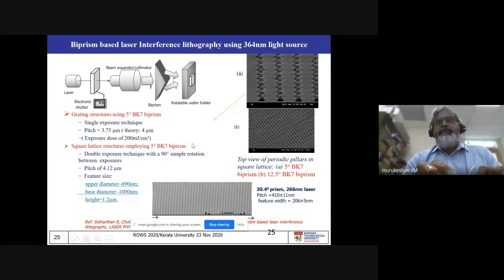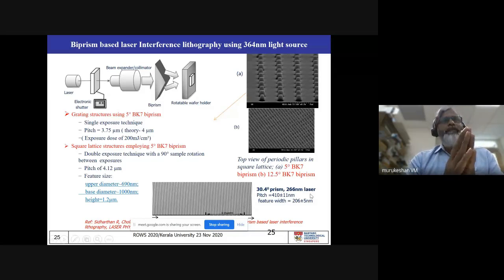Now, coming back to the feature size, you can see here that this is a single exposure technique. You can get a pitch of 3.75 micron, very close to the theoretical value, with an exposure dose of 200 millijoule per square centimeter. We can also get square lattice structures, and you can see that the diameter can be reduced up to 690 nanometer. If you increase this prism angle, the feature width can be reduced to 206 nanometer. You see this? We can reduce the feature size from micron to a few hundred nanometers, just using a biprism-based interferometer approach.